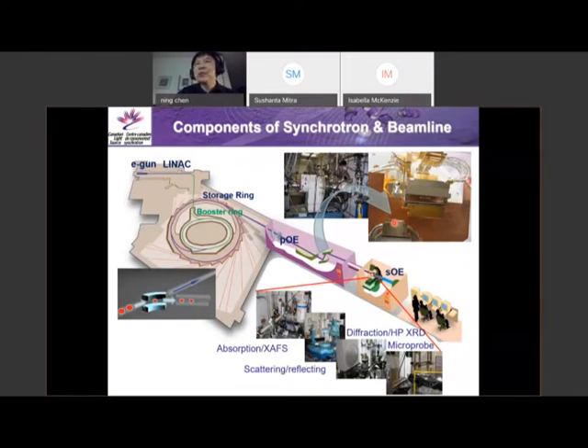We scan the angle, we select energy, and then the X-ray bounces up to the second crystal. The second crystal delivers the beam parallel to the SOE. Within the SOE, the X-ray will interact with our sample in different ways: either absorption, scattering, reflecting, or if we run powder, that's powder diffraction. Or we can tune the X-ray to a very small spot, and then we do microprobe.